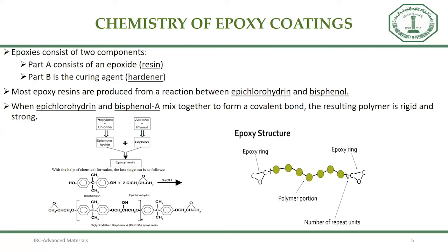So whenever I say epoxy coatings, it is made up of two different components. Component A is the epoxy resin, and component B is a hardener or curing agent. Mainly, the epoxy resins are prepared by the reaction between epichlorohydrin and bisphenol A. Here, 1 mole of bisphenol A reacts with 2 moles of epichlorohydrin in the presence of sodium hydroxide. It forms a diglycidyl ether of bisphenol A epoxy resin.